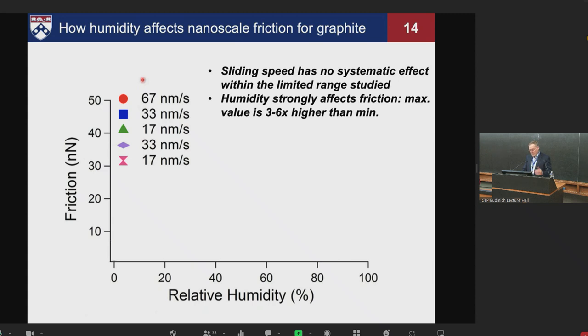When we measure friction with tips on graphite, friction's very low on graphite when it's dry. As we raise the humidity, we see an increase in friction. This is not too surprising. Many people have seen that when you start letting humidity in, often a capillary will form. That capillary will create an adhesive force between the tip and the sample that will increase the contact area, right? It's like you're adding load to the system because this capillary has surface tension, it has a Laplace pressure, it increases the load, and you get higher friction.